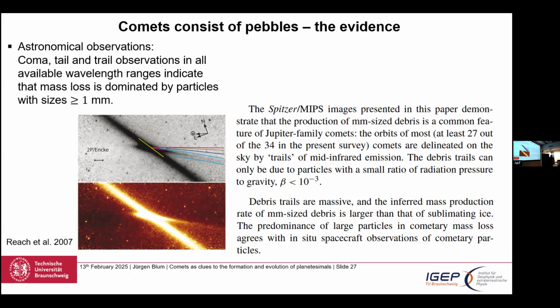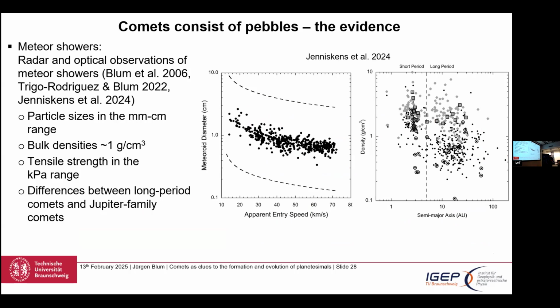For large particles, so beta smaller than 10 to the minus 3, they stay where they were formed. There's a little radiation pressure, so that distributes the particles along the orbit, but doesn't bring them away from the orbit. And the analysis showed that the beta values here are smaller than 10 to the minus 3, meaning that they are at least millimeters in size. So that's an indication that comets shed particles of millimeters or larger, which we can identify, of course, with pebbles, the formation pebbles.